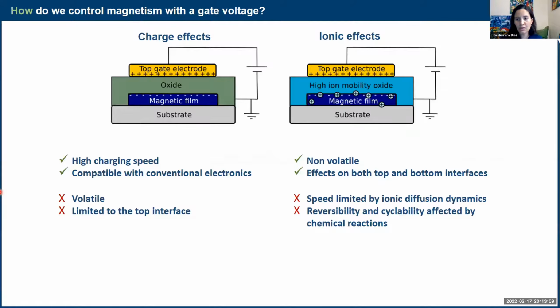So the electric field has to be high enough so that the ions can move. And then these ions can move towards or away from your magnetic film. And that is going to create large changes in the magnetic properties of the film. And the good side of this is that it's not volatile. Once the ions are wherever they are, you switch off your voltage and they're going to stay put. So that is an advantage. And of course, they can penetrate quite a bit into your device. So then the effect can be modulated between the top interface and the bottom interface. You can actually reach down to the bottom interface.